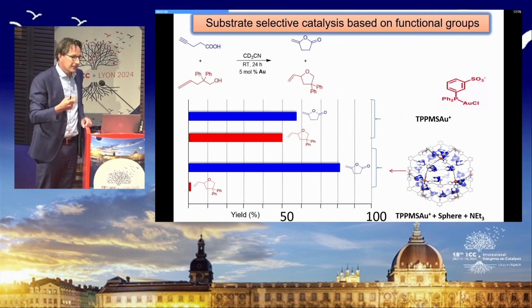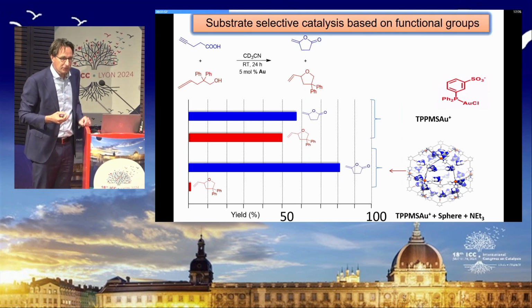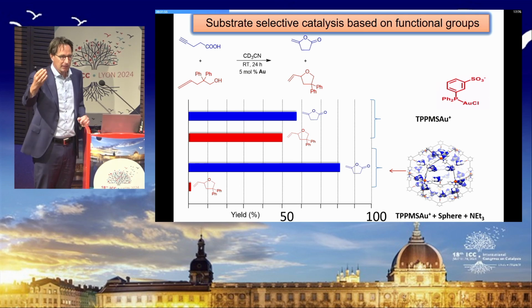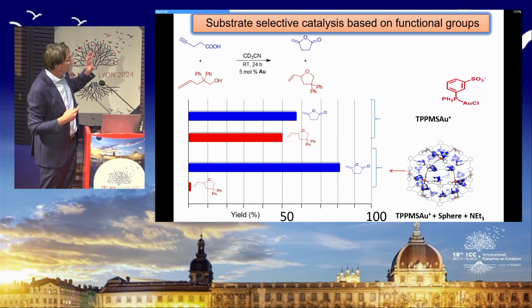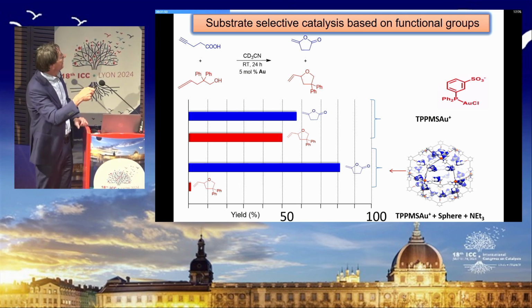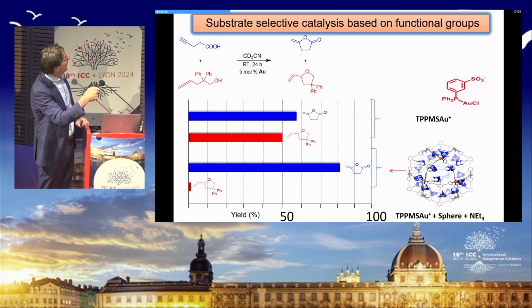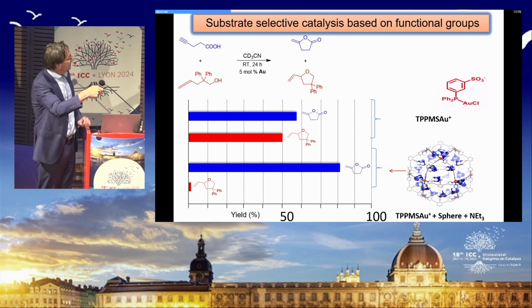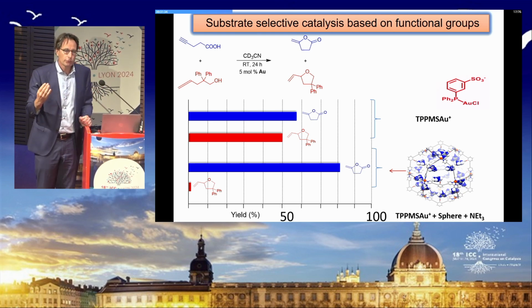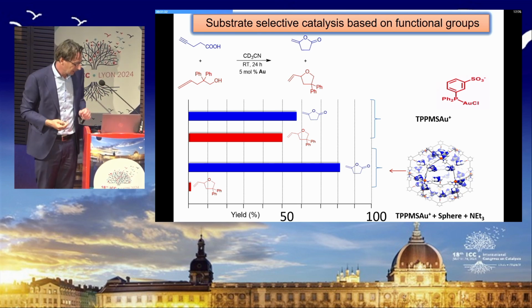We can also play a little bit with substrate selectivity, with a vision that maybe later in complex mixtures we can have control over reactivity. And here we mixed in a substrate that can bind with a substrate that cannot bind, that in the control experiment are converted in a similar fashion. But if you put your catalyst in this nanosphere, then only the substrate that binds is effectively converted. So you can use this cage for multiple tools if you like.